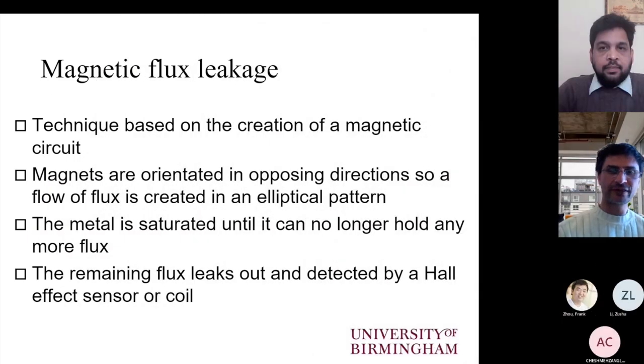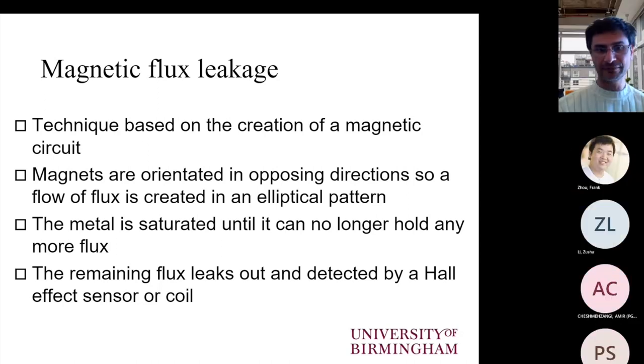So we'll start off with magnetic flux leakage, which, as I said earlier, is the earliest electromagnetic method for inspection of ferrous materials. This technique requires that we magnetize the sample, so it has to be ferrous. It cannot work with simply conductive materials, unless they are capable of being magnetized, then this technique is not applicable.